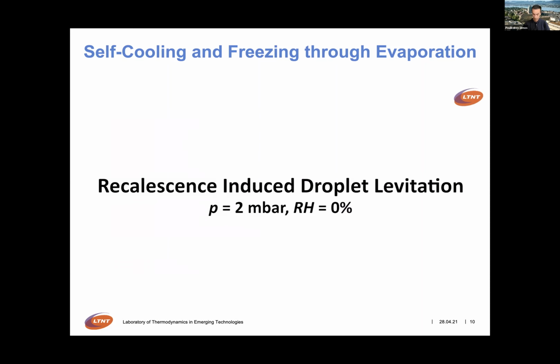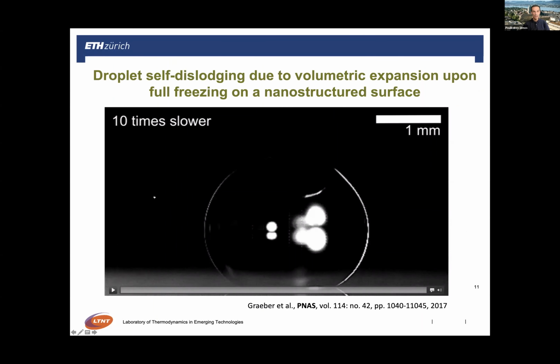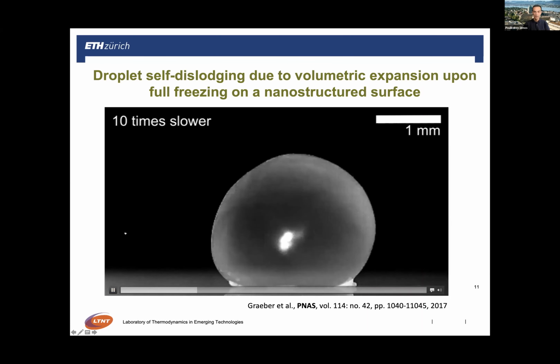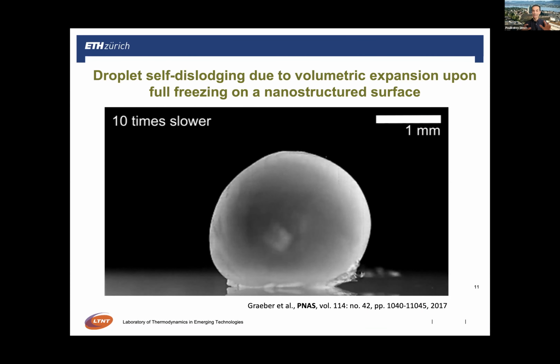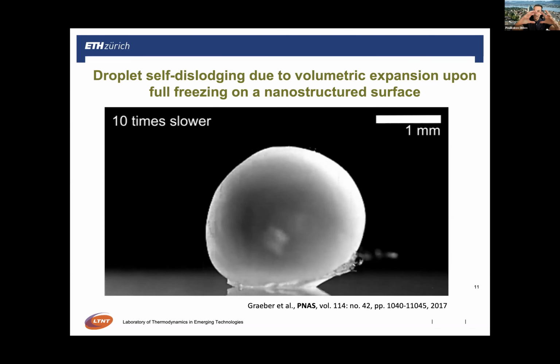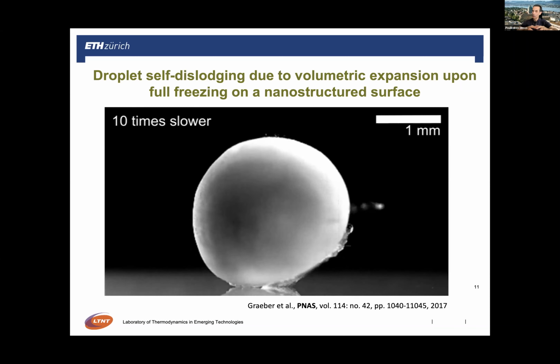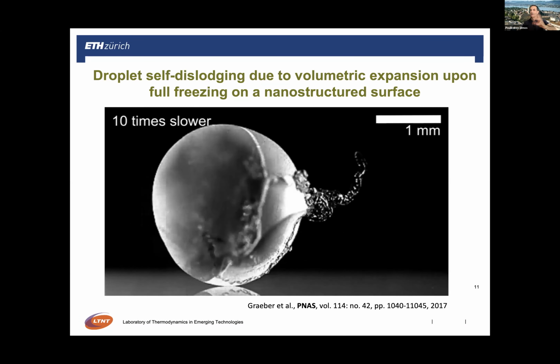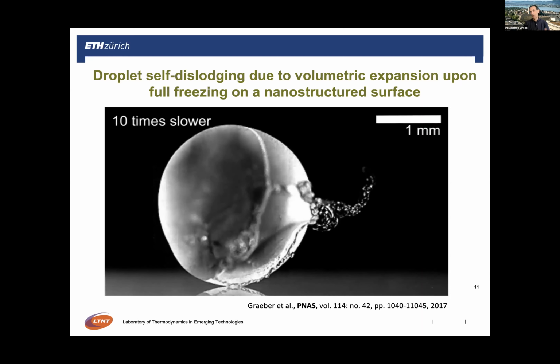One could exploit the second phase of nucleation as well, because here I have a similar situation, only the droplet, of course, does not go away every time. A lot of times it can stay on the surface, as you saw from the previous phenomenon. And if it stays on the surface, you can have a surface design that exploits the second part of the freezing process, which I show here. Now this droplet is on the surface, recalescence took place, and now the second phase comes, where you have effectively the shell growing from the outside inward and downward, and it pushes the ice sphere out of the surface by itself.